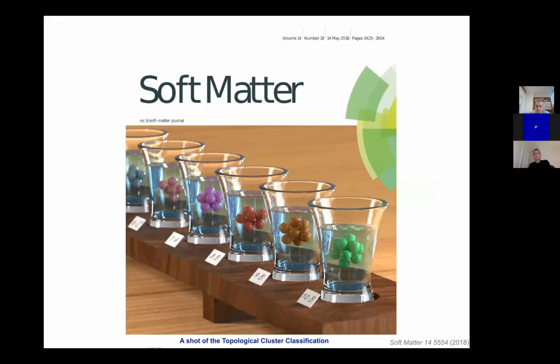Now, when we then come to analyze the data, we have developed a method called the Topological Cluster Classification. And what that does is identify structures which are illustrated here, and these are minimum energy structures of small numbers of particles. So if I took 10 particles, that's the green structure on the right, then they will assume a geometric configuration we refer to as the 10B. And if we take 9 particles, then there's a particular structure for those, 8 particles, and so on. And we look at all different minimum energy structures up to 13 particles. 13 particles is the icosahedron that I mentioned previously, which turns out to be a rather common structure in certain liquids.